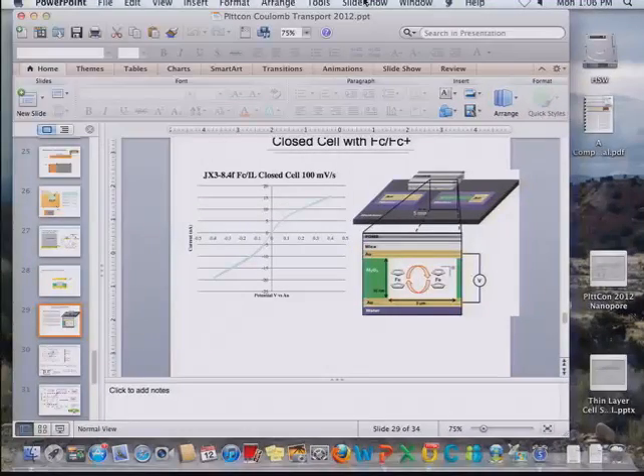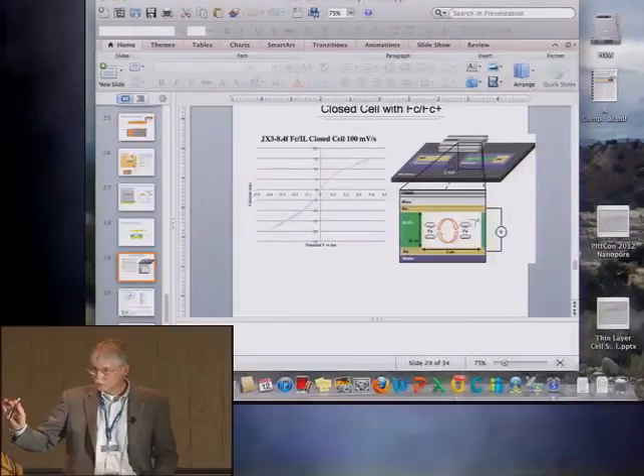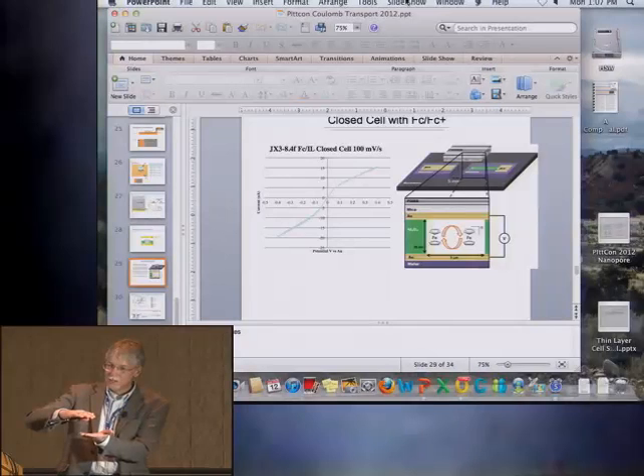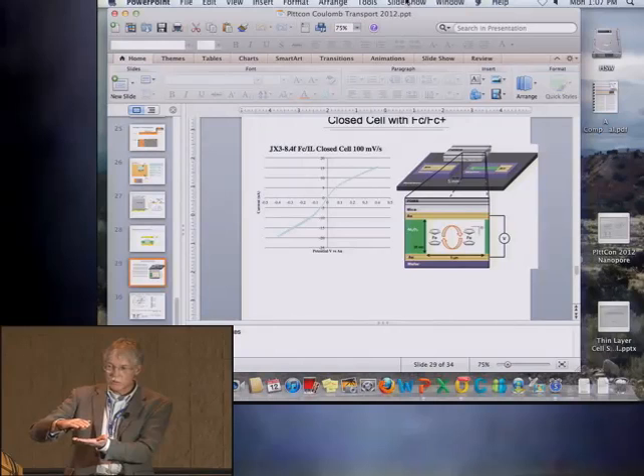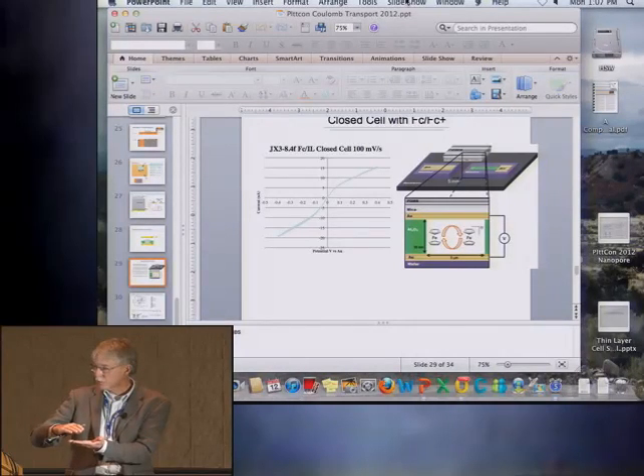All right, so here's electrochemistry. The solution contains ferrocene and ferrocenium. You scan positive, you get a wave; scan negative, it's perfectly symmetric. And the one thing I didn't tell you, but maybe I don't need to, is that if you have two gold electrodes, no matter what you put in between them, it doesn't matter what the solution is, you must obtain a symmetrical current voltage curve, symmetrical around the voltage axis and the current axis.